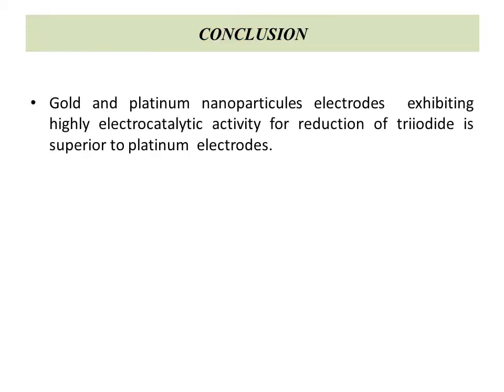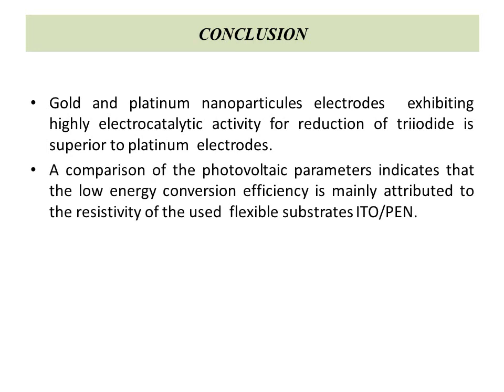In conclusion, gold and platinum nanoparticle electrodes exhibiting highly electrocatalytic activity for reduction of triiodide are superior to platinum electrodes, and the comparison of the photovoltaic parameters indicates that the low energy conversion efficiency is mainly attributed to the resistivity of the flexible substrate ITO.